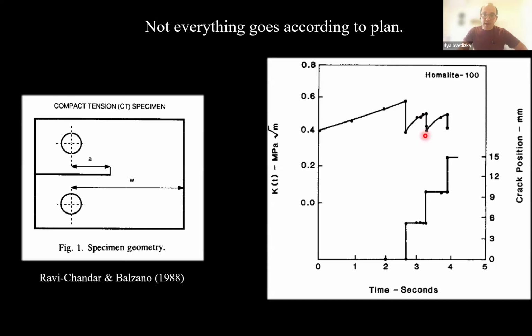Again, it jumps and stops between two values of the stress K. There is the critical one for nucleation, and there is the critical one for an arrest. And this ratio is about 10%. So keep this in mind.